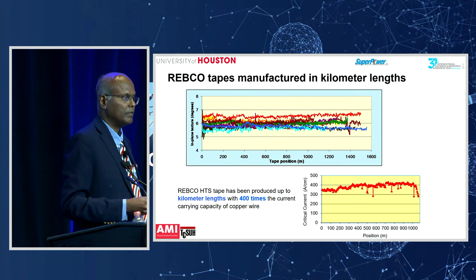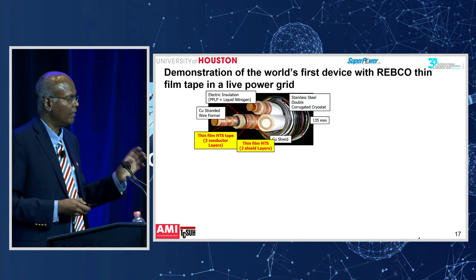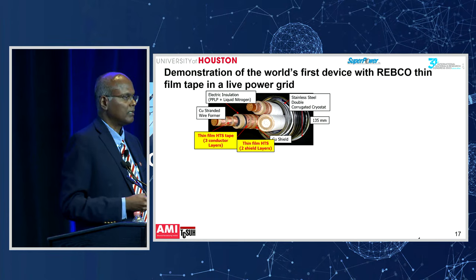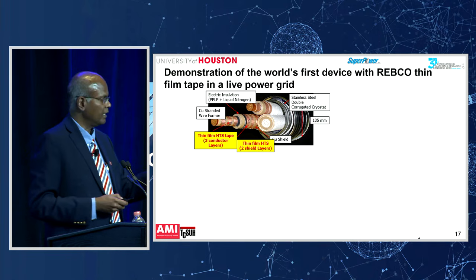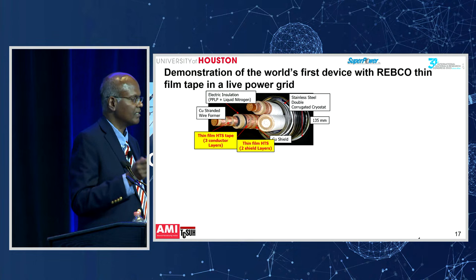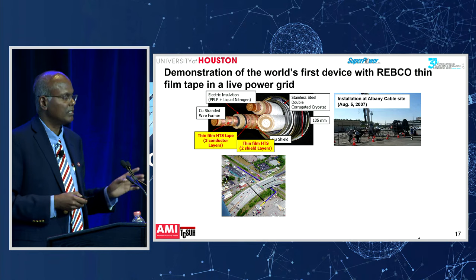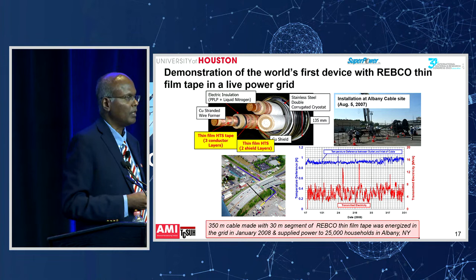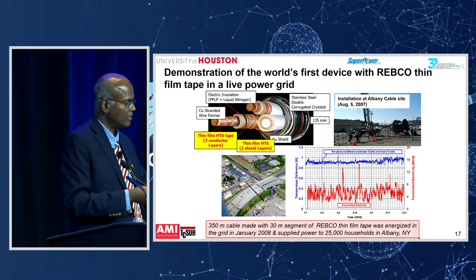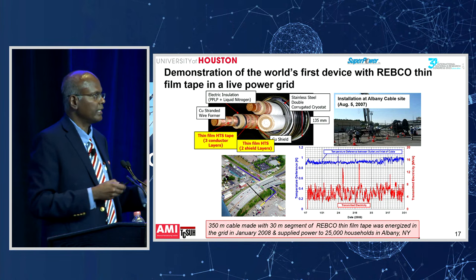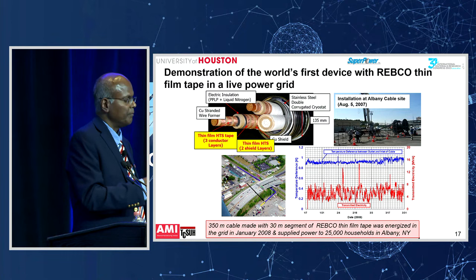And not only that, we actually installed this technology in the power grid. That shows a cutout of a power transmission cable. It's a three-phase power transmission cable, 36 kilovolt. What you see in the copper color is actually the superconductor tapes. It's a very, very thin material. Most of it is copper and other insulation and everything. You can see the photograph, it was installed back in 2007. On the bottom left side, you see Interstate Freeway I-90 going from Boston to Buffalo. It's installed under the freeway, and it delivered power to about 25,000 households. So this technology started from basic material science of how do you control grain orientation, and we brought it all the way to the power grid in a matter of about 10 years.